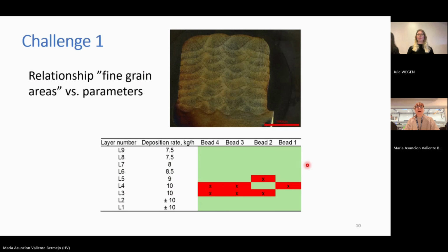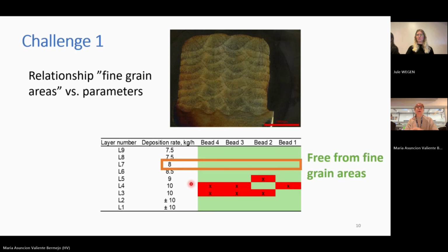Peter already explained that, but that is in parallel what we were developing together. So we also prepared experiments where we were changing the deposition rate, from higher to lower, until we found a good deposition rate, so that we are free from this fine grain area. As I told you, we were looking into different conditions in the same build, changing conditions and trying to identify the good or optimum operational window.